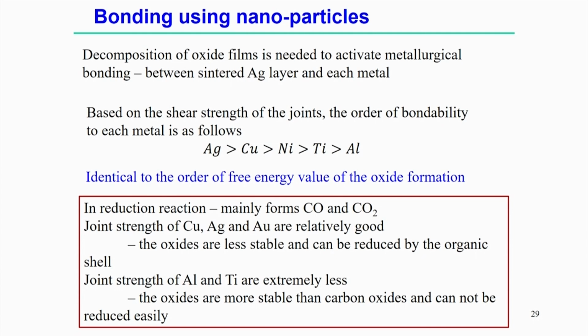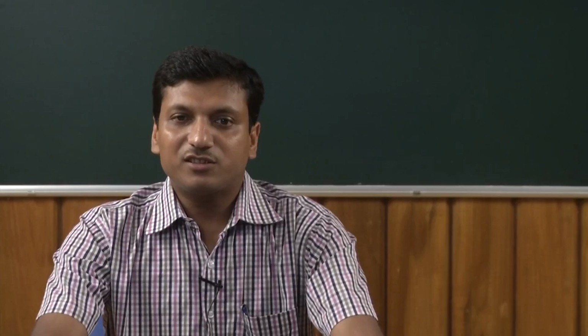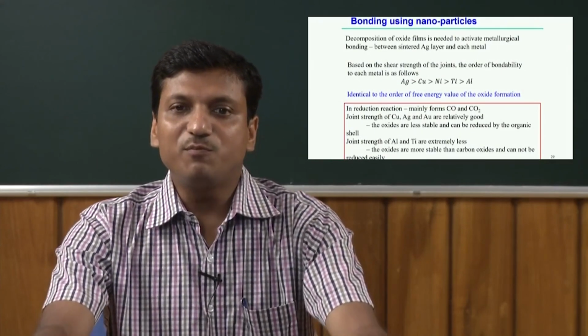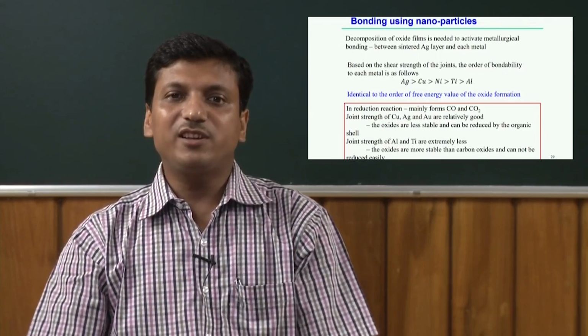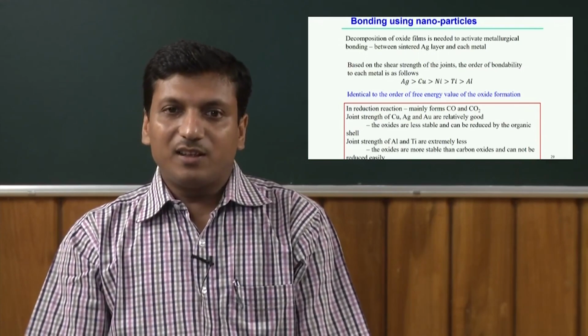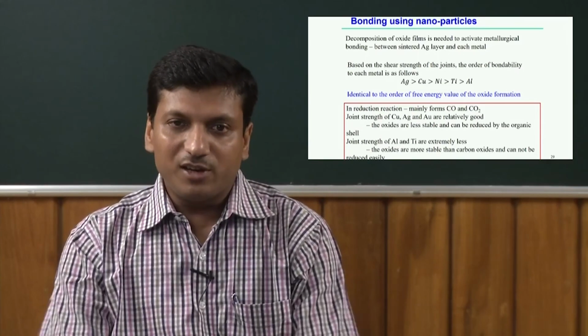Now, here you can see that based on the shear strength of the joints, the order of bondability of each material is given: silver, copper, nickel, titanium and aluminum alloy. Basically silver, copper and nickel have good bondability as compared to titanium and aluminum. This sequence follows the order of the free energy of oxide formation. If the oxide layer can be removed more easily by reduction, then using the nanoparticles we can obtain a very good joint as compared to other welding processes.